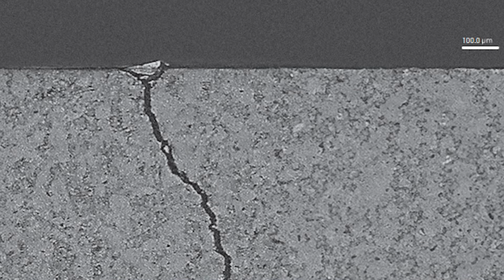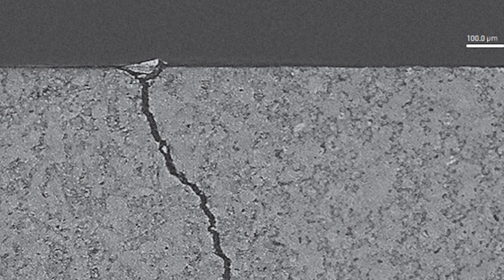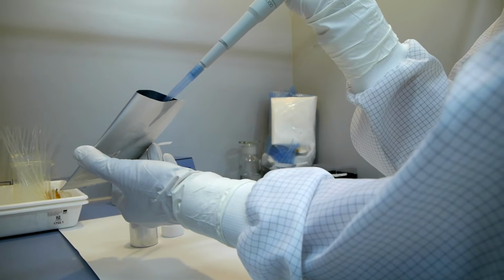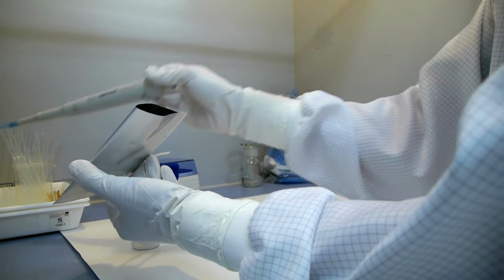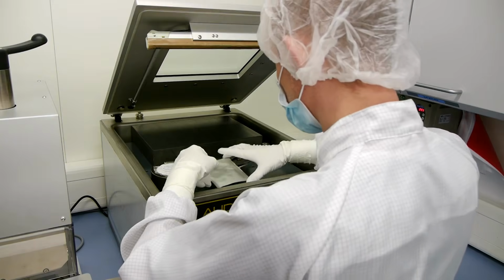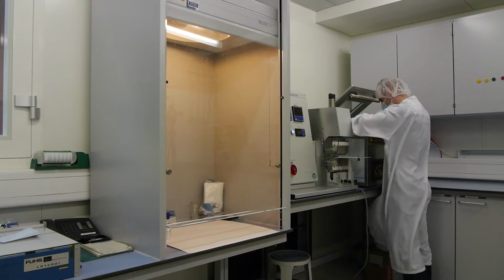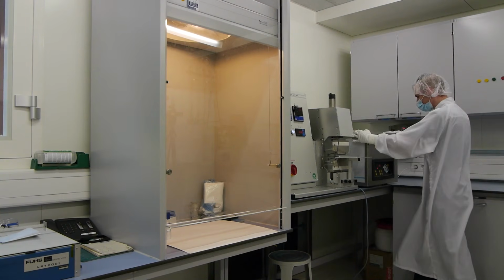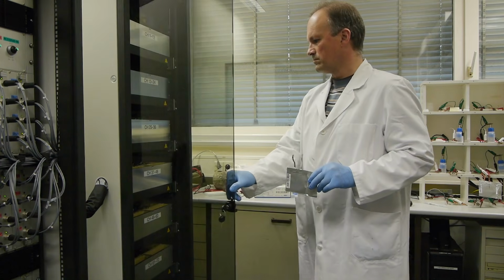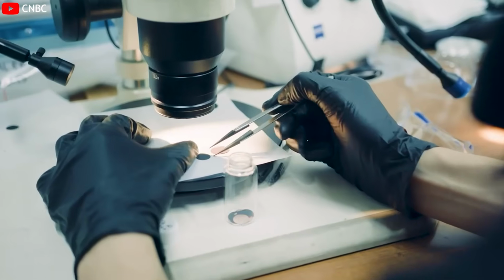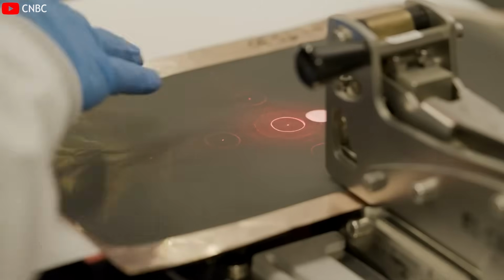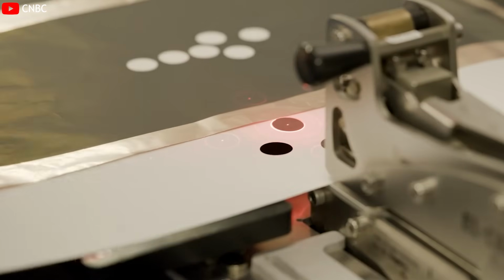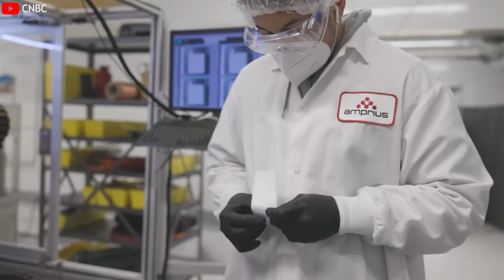Each crack exposes fresh anode material to the electrolyte. The battery repairs it, chemically consuming lithium and electrolyte in the process. This is internal self-consumption. Meanwhile, extreme core temperatures can boil and decompose the electrolyte, generating gas. Cells swell. Mechanical stress spreads through the pack structure. The fans stop. The display says, "Ready to drive." The damage is already done.